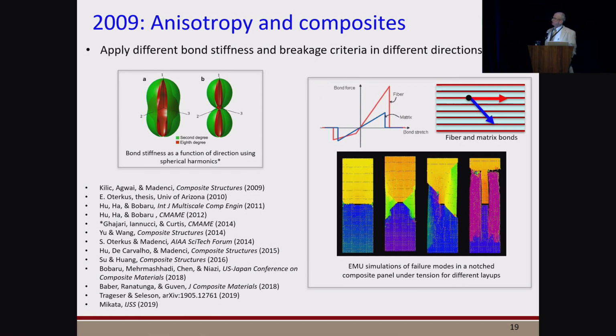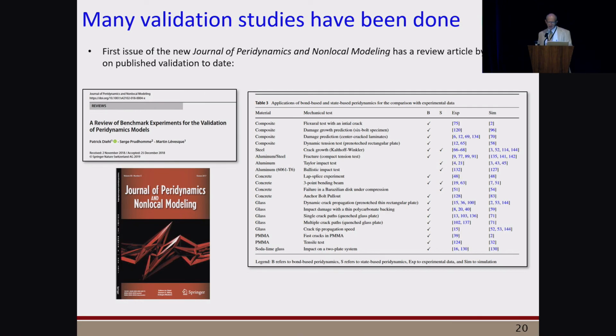Anisotropy can be modeled by allowing the bond properties to vary with direction. So in a lamina, in a unidirectionally reinforced composite, you can have bonds that are parallel to the fibers much stiffer and stronger than all the other bonds. You can also have the bond properties vary continuously according to some function like this spherical harmonic pattern that's shown here. So just using these concepts of anisotropy, you can reproduce a lot of realistic features of damage and fracture in composite laminates that are used in the aerospace industry.